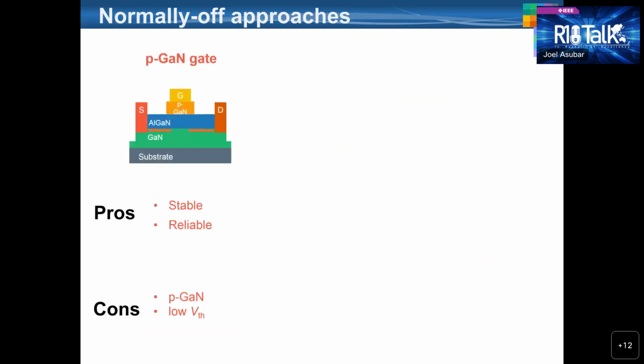So the big question now is, how do we obtain normally off operation with positive threshold voltage? There are different approaches, and these include the P-GaN gate. For a P-GaN gate, a P-type gallium nitride is inserted between the gate and AlGaN, causing the depletion of the 2D channel. Well, it has its pros and cons. Its advantages are that it is relatively stable and reliable, but the threshold voltage is very limited, up to positive 1.2 volts. And of course, it includes a very unreliable P-type GaN layer.